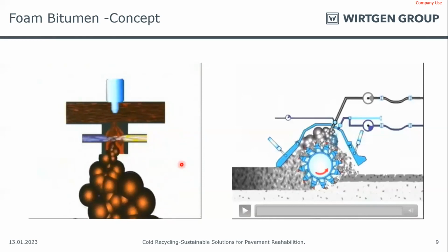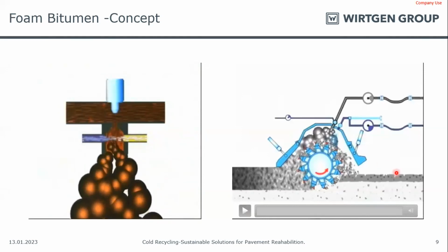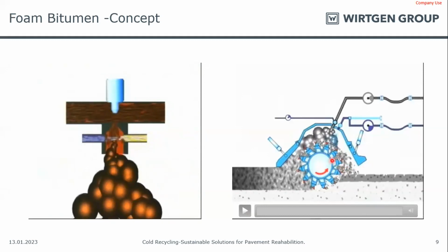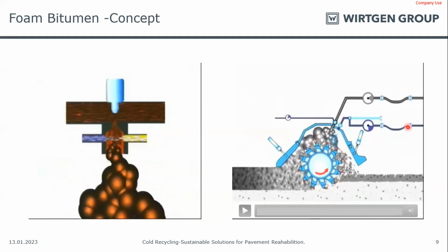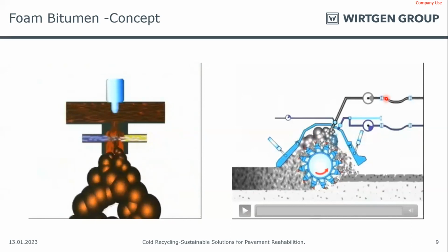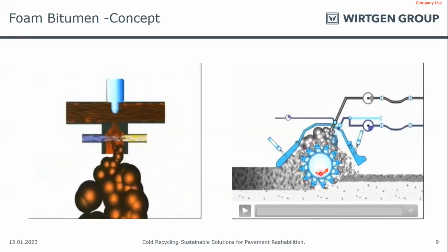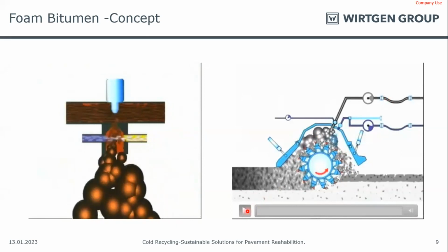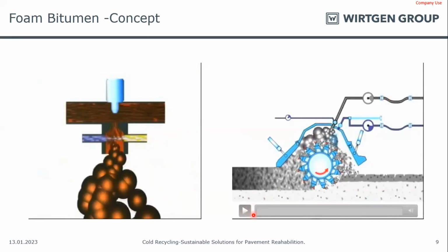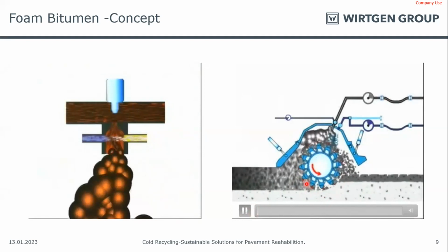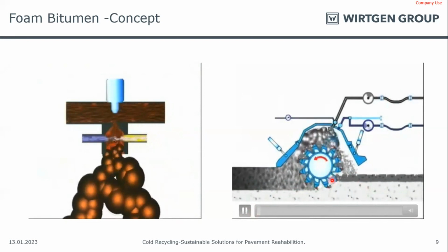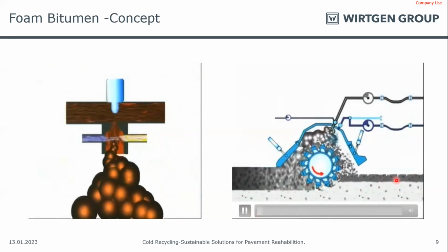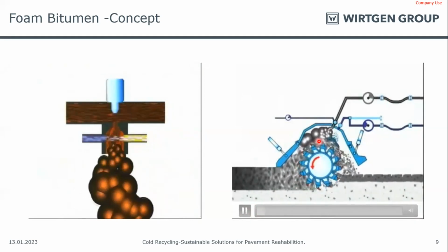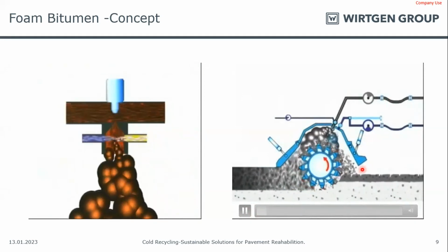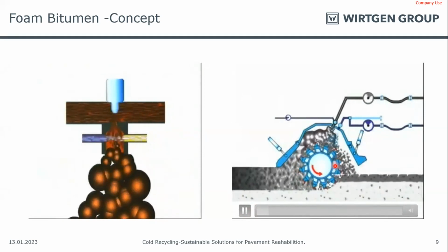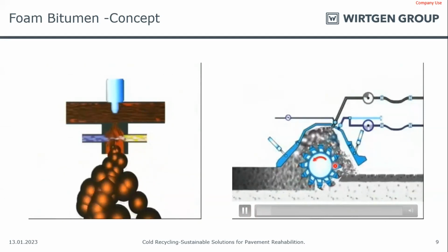All this process happens inside the mixing chamber of the machine. On the right hand side, you can see the mixing chamber, which is inside the machine. We have the water line as well as the bitumen line attached to the machine. This drum granulates the existing asphalt layer and mixes it with the pre-spread cement and the foam bitumen. So we get a BSM layer, that is the bitumen stabilized material. All this process happens inside the machine itself.